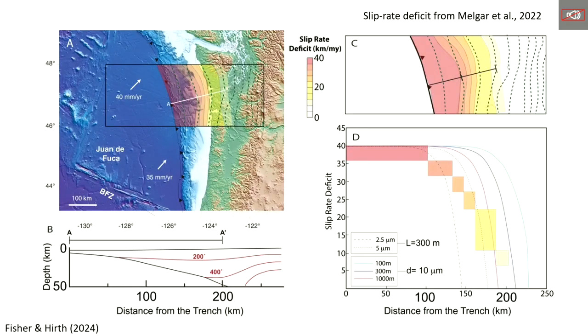So the last bit here is to say, if we look at the geodetic data for where we're standing, and look at estimates for the slip rate deficit as a function of depth, you get something like this, where it's locked up here, and then you start to see deviations from that, getting down to like 0 at around a distance from the trench of about 200 kilometers. So where the temperature is getting around 400 degrees.